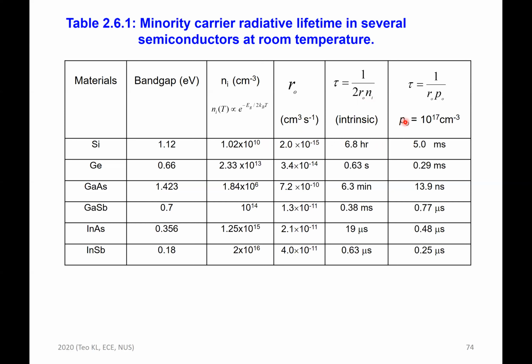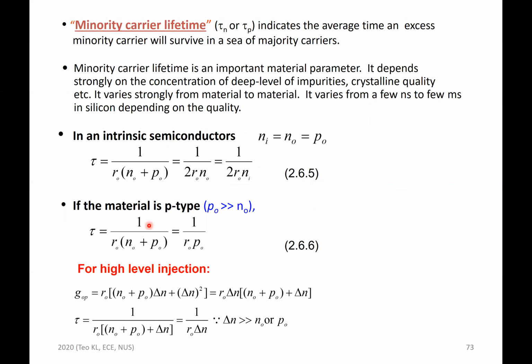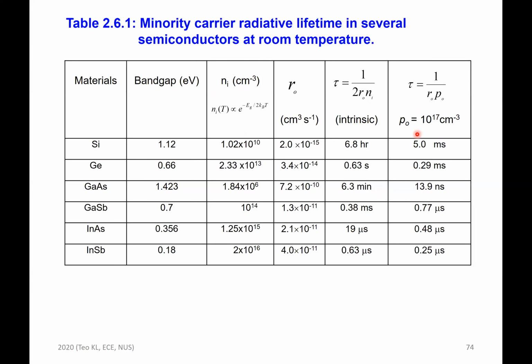If you do it with p-type, the recombination lifetime will be of this expression. So let's say p naught is 10 to 17, you reduce to 5 milliseconds. So you can see that silicon, in view of the fact that it's an indirect bandgap semiconductor, the recombination lifetime in intrinsic semiconductor is 6.8 hours. It's not very efficient for light emission. You want to have the recombination